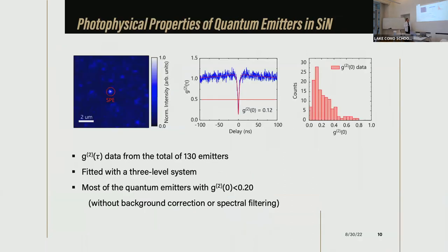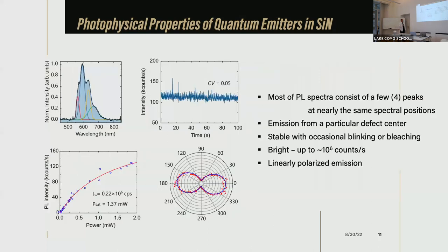So here are some results. In this particular case, we studied 130 emitters, and this is G2, the autocorrelation function, typically used to show how single these photons really are. So the smaller the G2, the better, and you could see the histogram, so you could see that for most of them, G2 is way below 0.2. And that is without any background correction or spectral filtering. In this case, it goes down to 0.12. So as I already mentioned, they all peaked around the same spectral range. Or you could actually say there might be four overlapping peaks. But when you move from one point to another, it still looks very similar.